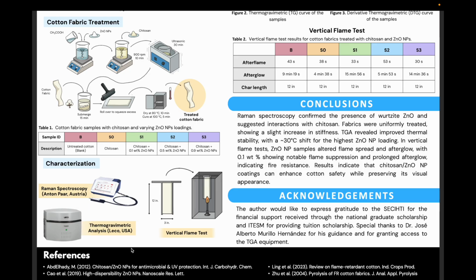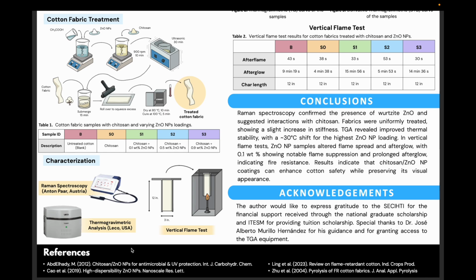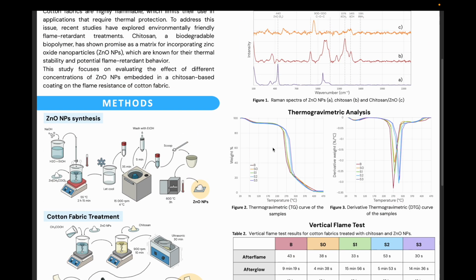In this test, a 12 inches by 3 inches sample was subjected to a methane flame for 12 seconds. 3 parameters were recorded. One was the duration of the visible flame after removal from the fire. Another is the duration of the afterglow, which is the slow burning of the fabric, and the char length of the sample after self-extinguishing.